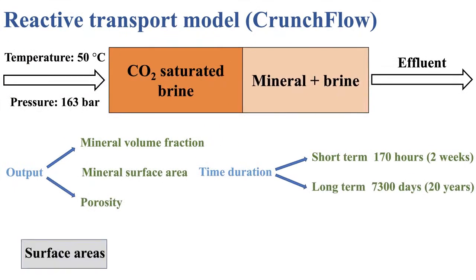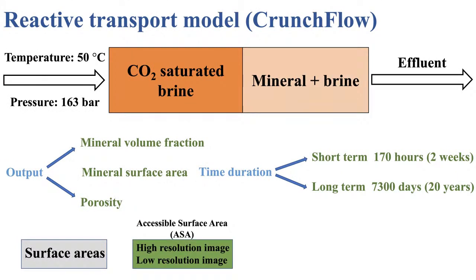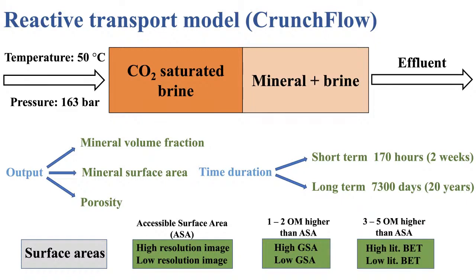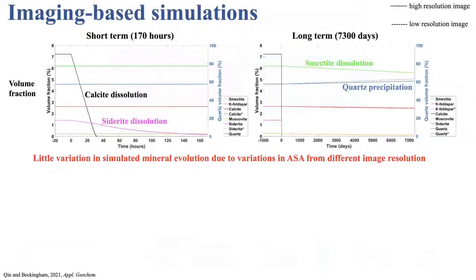We looked at a variety of different surface areas. So the surface areas from the highest and lowest resolution images, but then also surface areas from traditional approximations, including 2 geometric surface areas, which are about 1 to 2 orders of magnitude higher than the accessible surface areas, and then 2 specific surface areas from the BET measurement in the lab, which are even higher than the geometric surface areas. We're not going to go through all of the results, but I'm going to show you some of the highlights here.